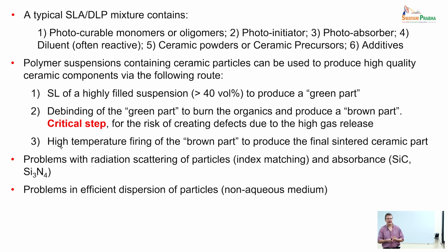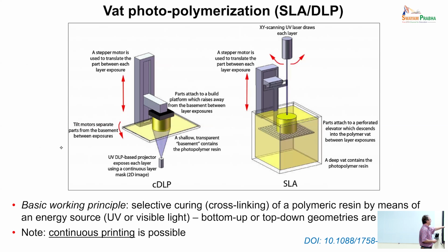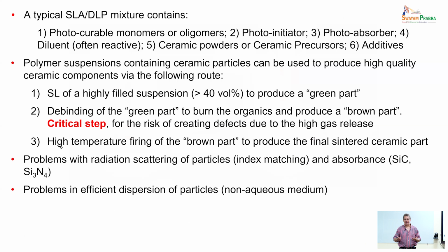And this means that if you go back here, you know that every time you shift the layer, you shift the part, the gap needs to be filled by your feedstock. And if the feedstock does not flow because it contains a lot of particles, then you have issues in terms of the homogeneity of the next layer that you're generating.